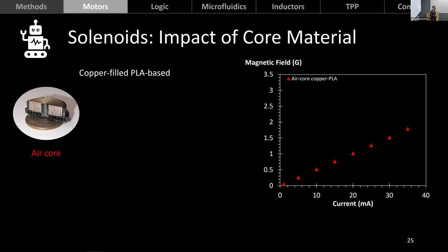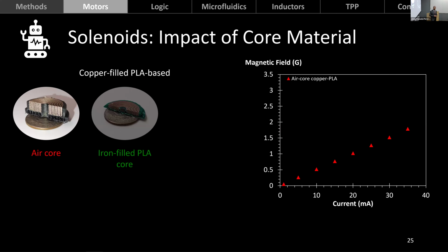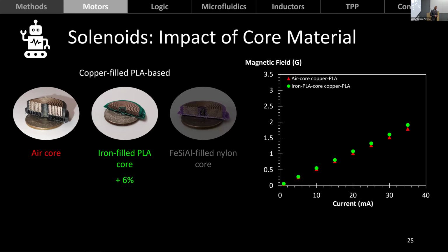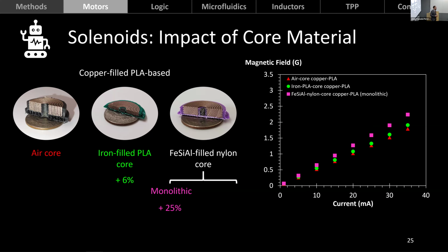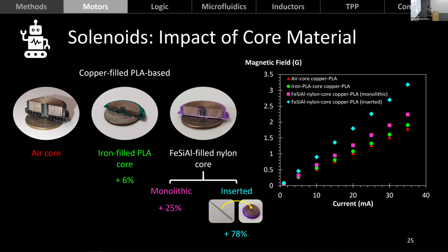And so then we started adding magnetic cores, first with the iron filled PLA filament, which gave us about a 6% increase in magnetic field. And then with the FeSiAl filled nylon, the one coming from pellets, both in its monolithic implementation, which gave us about a 25% increase, and in its inserted implementation, which gave us almost an 80% increase. So there is a pretty nice noticeable improvement, and it demonstrates that there is a lot of potential in these core materials and including these cores in the solenoids.